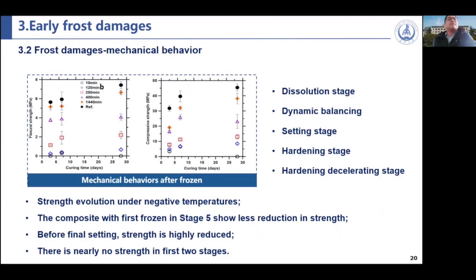We measure the strength. We can see the strength still develops under the negative temperature, and the composites with the first frozen in the hardening decelerated stage show less reduction in the strength. Just the black point and the red point you can see are very nearly close.